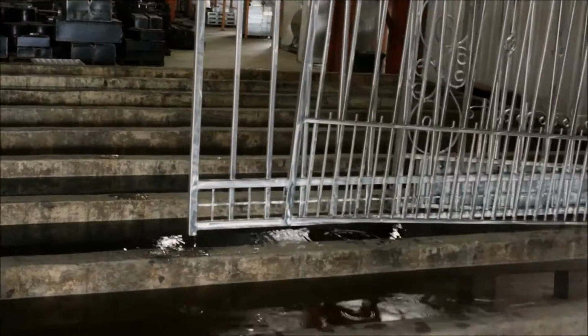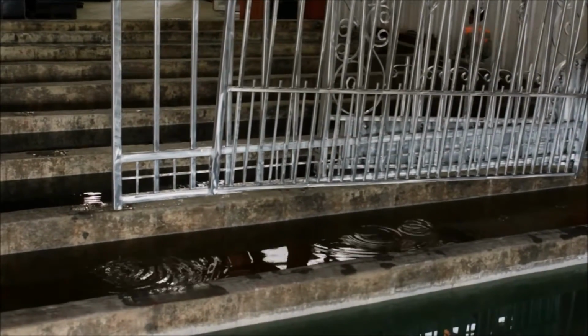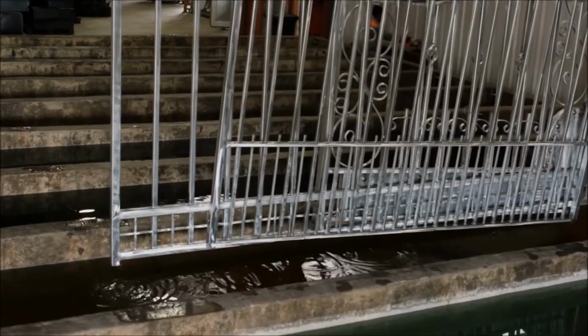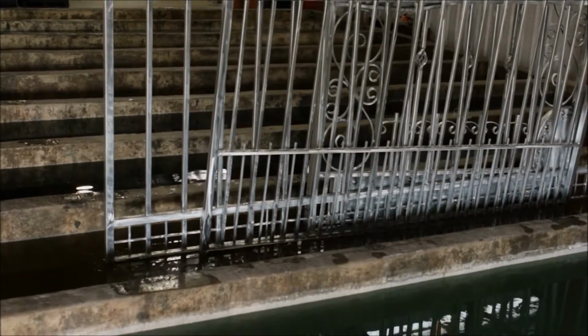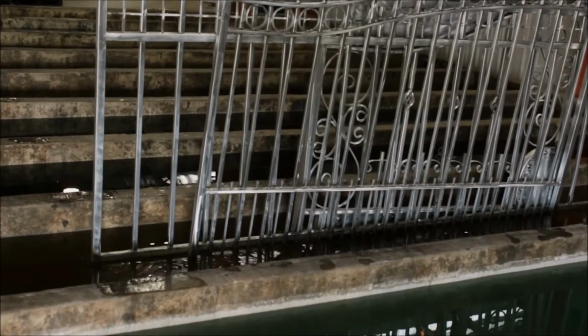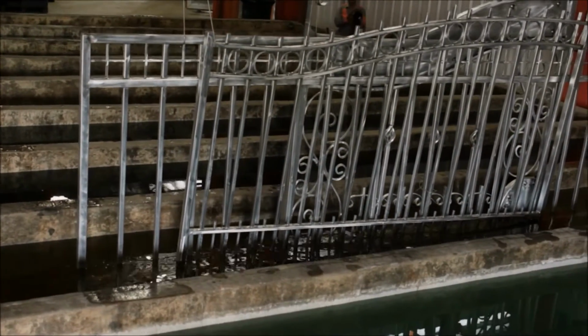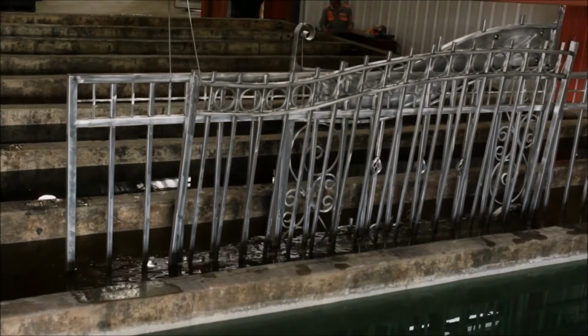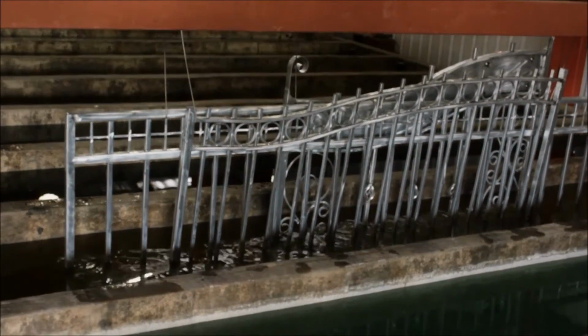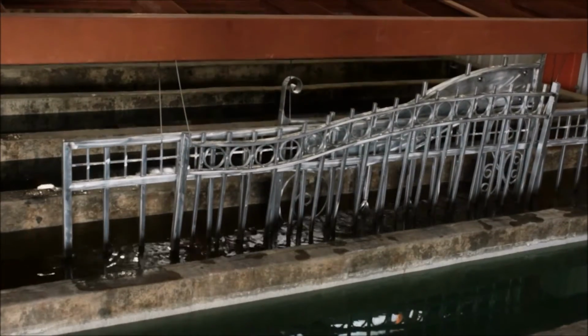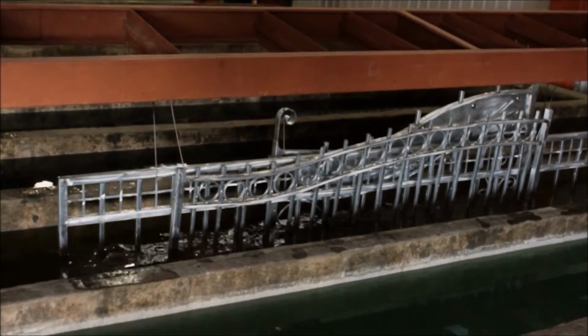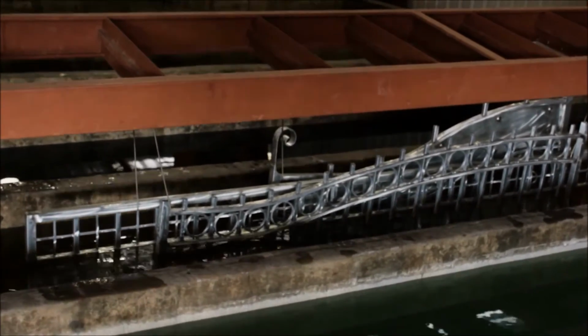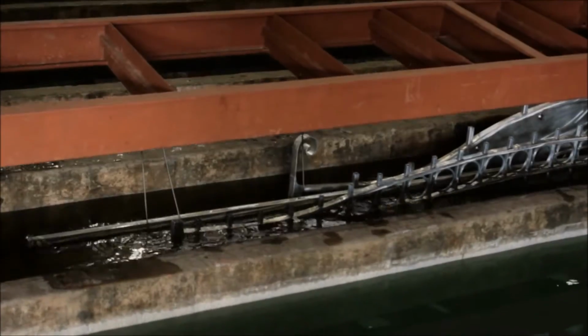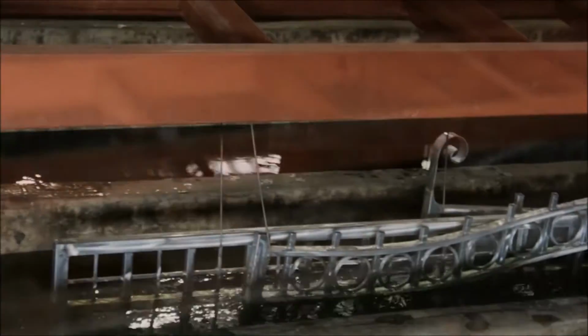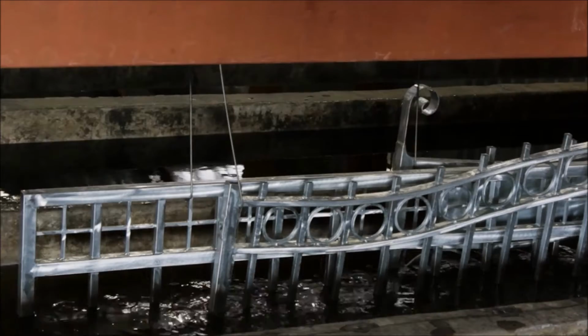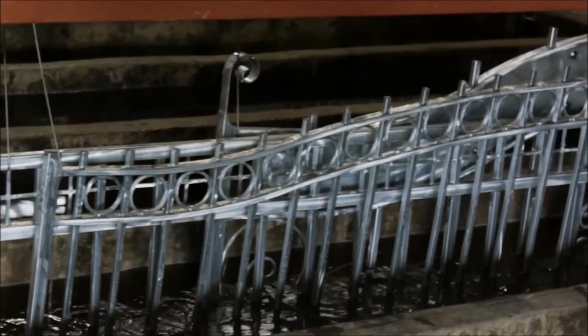So prior to actual powder coating, the product goes through a chemical pre-treatment process, which starts off with a degreasing solution and then 2 rinse baths, and then it goes into an activating bath, and then a zinc phosphate bath, and then a rinse, and then it gets dried off prior to putting it onto the powder coating line. The zinc phosphating is a very important stage of the painting process, because otherwise the surface is too smooth, and then over time the powder coating will peel off the zinc.